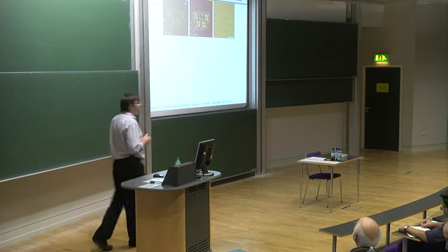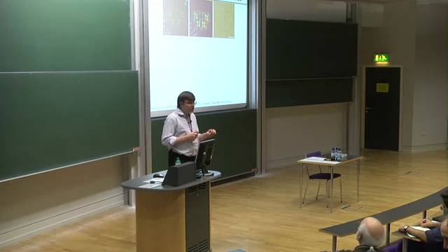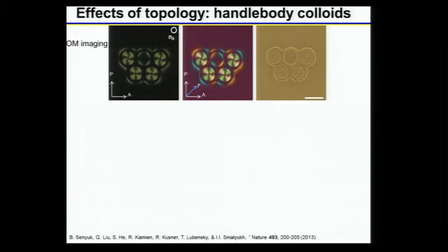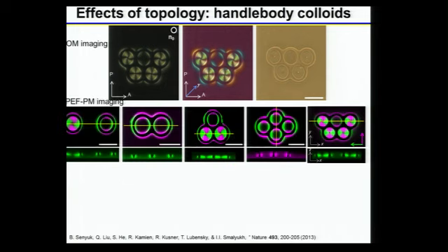So let us see what happens if we introduce a colloidal particle that has 5 holes. That means the genus of this particle is 5, into a liquid crystal. You can see a number of different defects that are observed, you can see in those polarizing microscopy textures. Now we can do three-dimensional nonlinear optical imaging by means of multi-photon fluorescence.